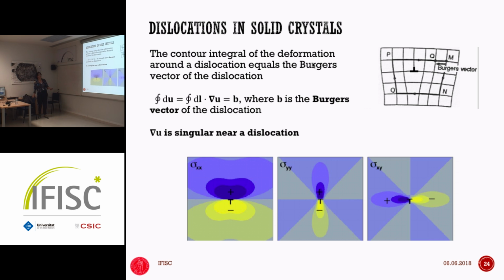So for example, it's the same as with the vortex in a field. If you do a contour integral around the dislocation, no matter how far away the contour is, you're going to pick up a phase. So it's not going to be equal to 0 as it would be for an affine transformation. In this case, if we start here and make a loop around it, and I go 4 lattice sites this way, and also 4 lattice sites the other way, you see that there is a gap. I can never close the loop. I come up with something, and that's what's called the Burgers vector.